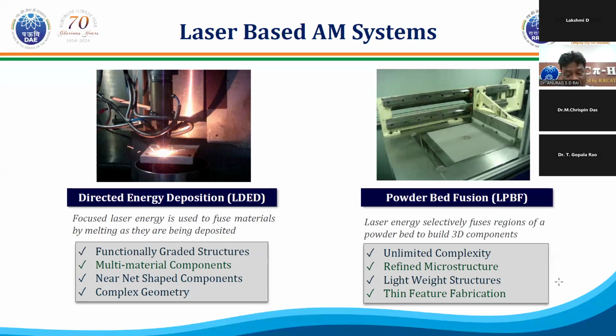In such cases, you can go for unlimited complexities. Since the layer is thin, you have a very massive structure working as a sink for the heated metal powder, so we get very refined microstructures. And since we are able to make porous structures, it's possible to build lightweight structures, and thin feature fabrication is possible. When I talk of thin features, you can have structures as thin as a few hundreds of microns. We could make up to 250 micron very nicely, and these structures can be used in various applications that are otherwise not possible.